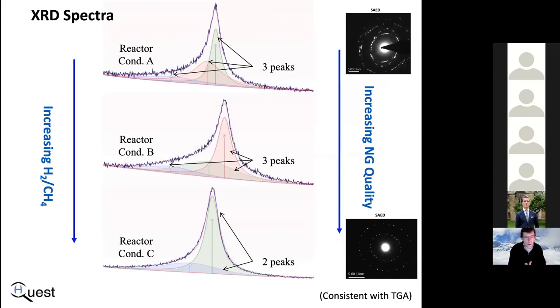Again, it's a short talk, but I'll just mention another dimension to that design of experiments methodology. In this case, it was exploring the hydrogen to methane ratio. Under 3 nominal reactor conditions, A, B, C, each with a monotonically, distinctly higher hydrogen to methane ratio, you can see that the XRD peak of the bulk solid carbon produced shifts not only in terms of angle, but also becomes much more preferential for one main peak, that being of the nanographene.